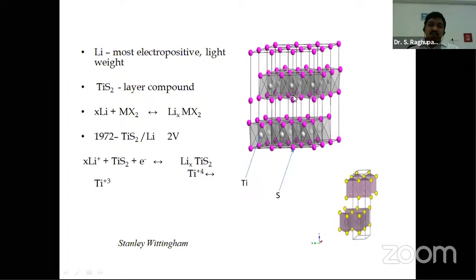If it exceeds 15%, what will happen? The structure will get destabilized and it will collapse. That means the host structure will not be available for us. So while the guest species here is lithium ions, while lithium ions are entering, there must be space in the host. This material was explored by Stanley Whittingham in the early days of lithium ion batteries. So here the lithium ion battery was introduced, but the voltage we achieved is 2 volts. Still it is very close to the lead acid battery we were using at that time.